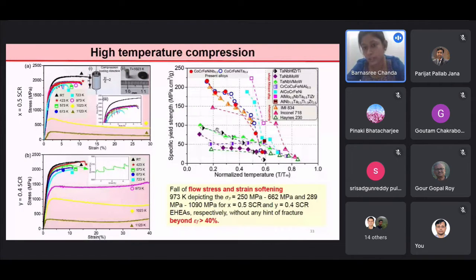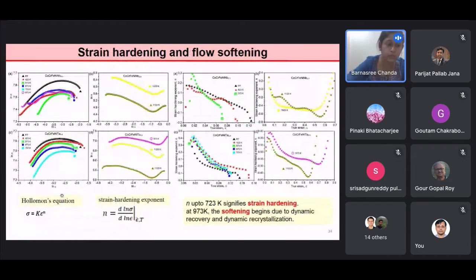The specific yield strength versus normalized temperature plot is compared with refractory high entropy alloys, aluminum-based high entropy alloys, and conventional superalloys. We see that the specific yield strength variation with normalized temperature is comparable with the conventional superalloys and other alloys. Next, strain hardening and flow softening behavior. Hollomon's equation, which correlates the flow true stress and true strain under deformation at constant strain rate and temperature, shows the variation.